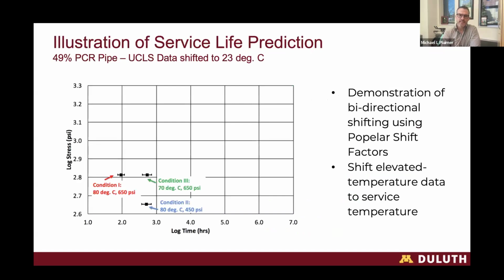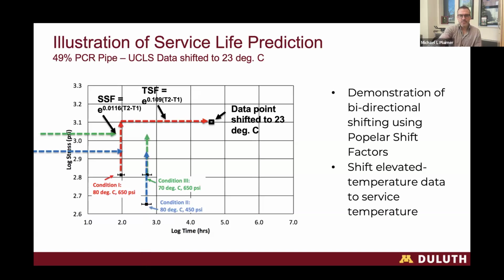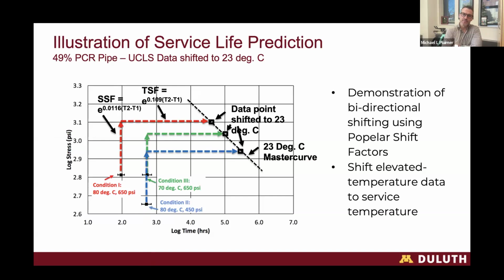So basically, we require the testing to be conducted at multiple temperature stress conditions. Condition 1 is at 80 degrees C and 650 psi stress, for example. Condition 2 at 80 degrees C and 450 psi. Condition 3 at 70 and 650. And then we apply these shift factors to those failed data points at each of these conditions to get what we call a master curve, which is a prediction or a projection of how long it would take these materials to fail in that brittle crack stress mechanism under various stresses at different temperatures. So in this case, we're shifting the data to 23 degrees C, which is about ambient temperature.